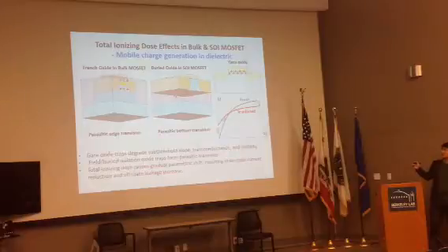And if these charges are localized on the surface of the dielectric, at the sidewall of the transistor, then these positive charges can act as a constantly, partially turned-on parasitic transistor that connects to the main transistor in parallel.